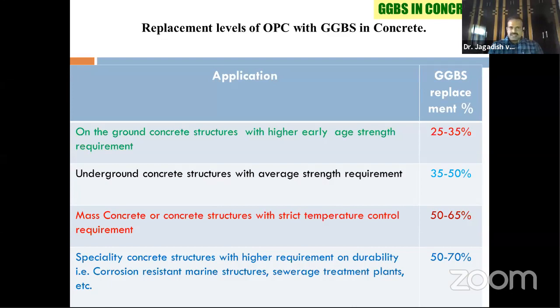When it comes to GGBS, the replacement levels of OPC. Okay, before explaining this, I'll just give you an overview. You all know ordinary Portland cement, then Portland pozzolana cement, wherein fly ash is replaced up to a percentage of 35% in cement. I'm talking about Portland pozzolana cement, wherein you add the fly ash. And in Portland slag cement, they go up to 65% replacement. I'm talking about cement manufacturing, OPC, PPC, and PSC. But when you are adding supplementary cementitious material directly to the concrete, the replacement levels based on different works all over the world are like this.